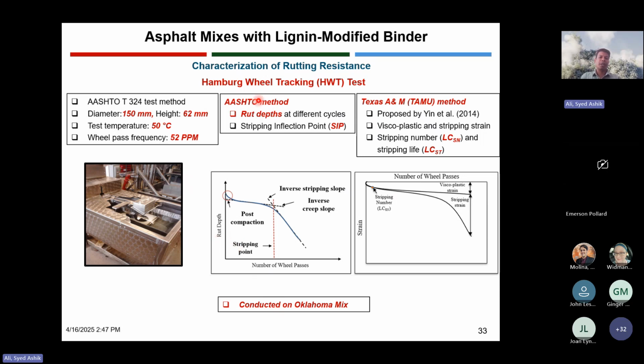For rutting, we used the Hamburg wheel tracking test, with a 150 millimeter diameter sample with 62 millimeter height. The test was done at 50 degrees Celsius, and the wheel pass frequency was 52 passes per minute. We used the AASHTO method, where we looked at the rut depth at different cycles and also the stripping inflection point for moisture-induced damage. The Texas A&M or TAMU method is another method that is getting popular with many DOTs and many agencies. So we wanted to use that too.